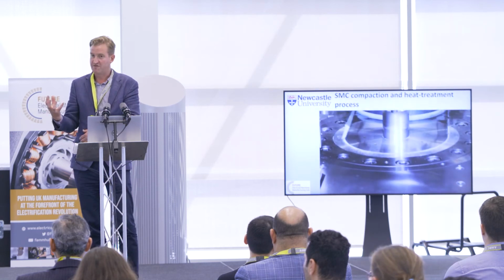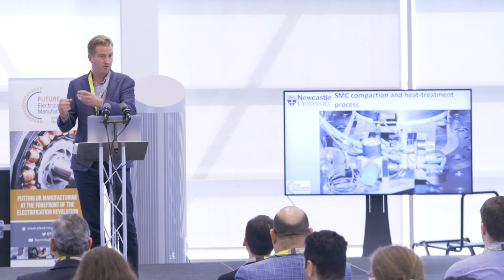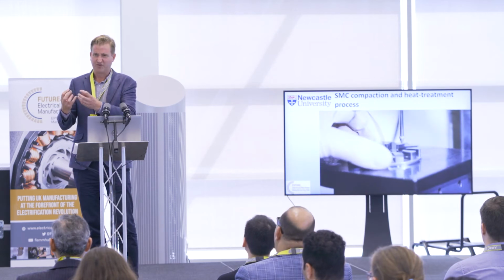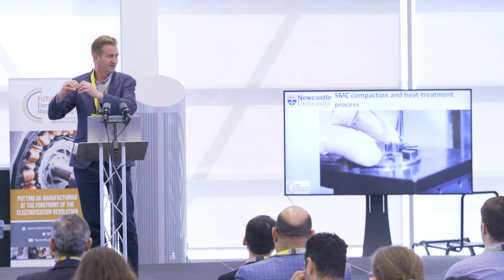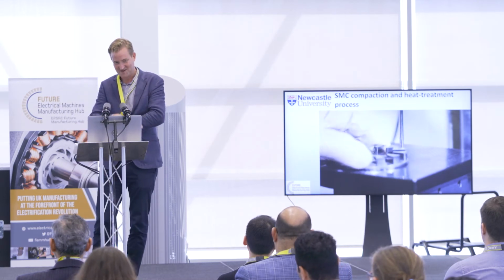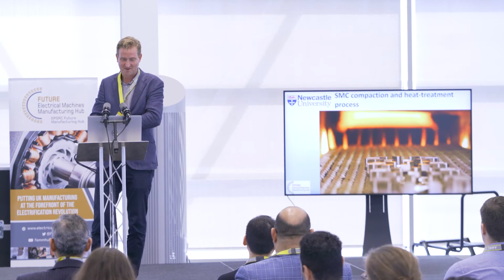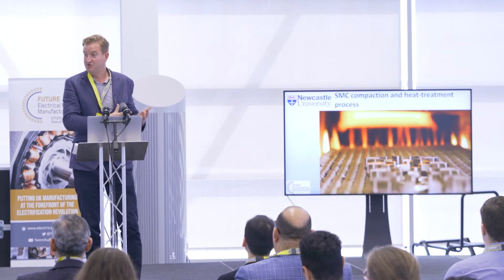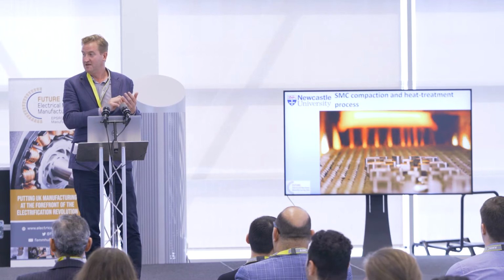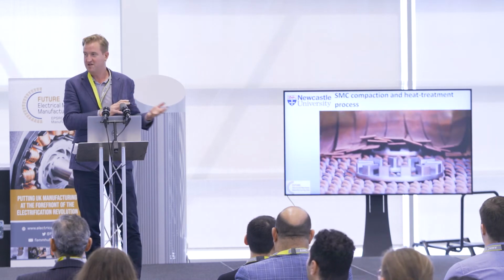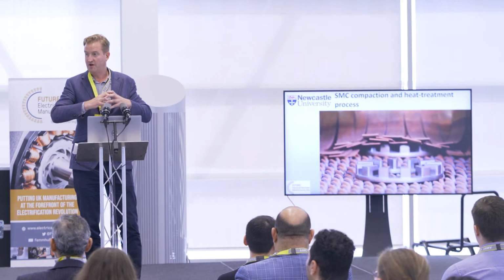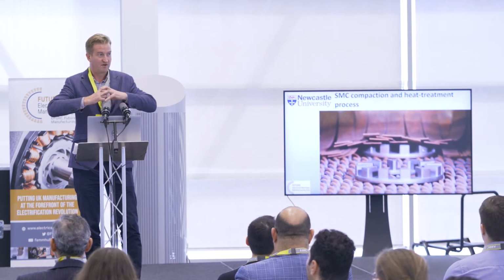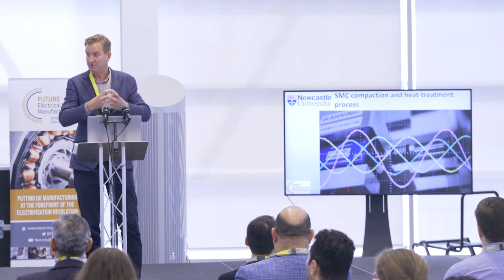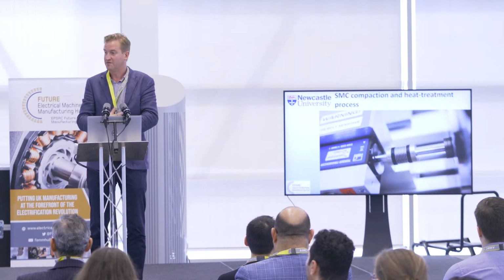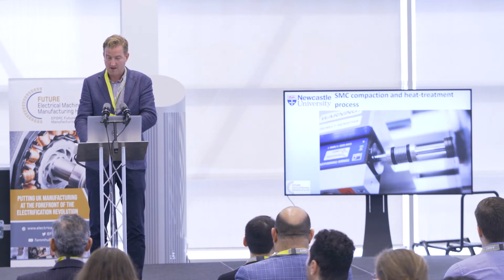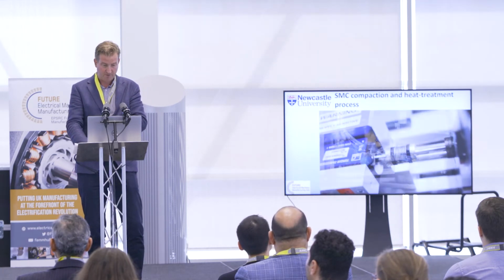When they come off the press, they're in what we call the green state. They're not mechanically strong. They've got the kind of consistency of a ginger nut biscuit. You can break those bits off. This is just a little bit of measurement to check the size of them. Once they come off, they're then heat treated. It's not sintering. That's the point. The temperature is between 550 and 650 degrees, depending on the properties you want. That relaxes the stresses in the material. It helps the thing hold together, and it comes out with a much greater mechanical strength than the initially green state pressed components.